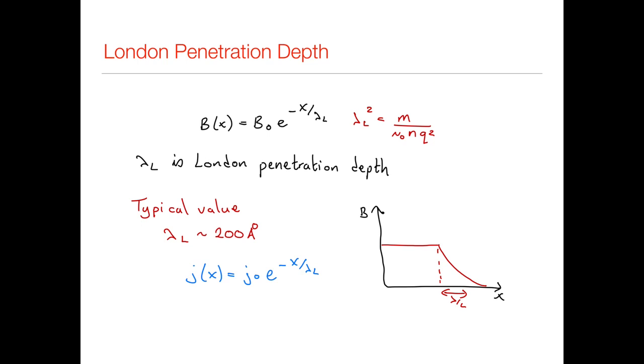So what that means is that this depth is going to get longer. We're going to expect something like this to get longer and longer. So as we approach Tc, the magnetic field can penetrate deeper and deeper into the material, and at Tc itself, n will go to 0, and hence the penetration depth is infinite. So the material has now become normal, and the magnetic field has been able to penetrate completely through the material. Okay, so I just thought we'd look at that as a consequence.